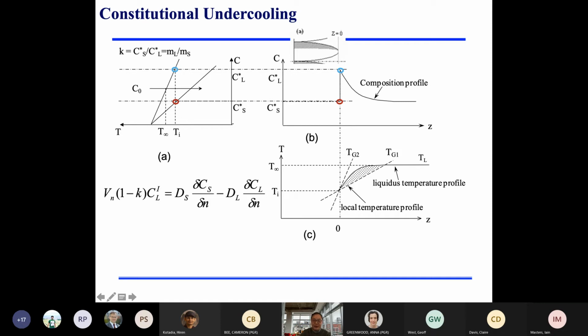So you have this one, and then you can apply different thermal gradients. Look at TG1, TG2. If TG2 condition, then any material that forms or solidifies will be melted. And if TG1 condition, you get what we call a constitutionally undercooled area, where you can form new grains, or if a new grain forms, it can grow. So this is a concept called constitutional undercooling, and this is mainly